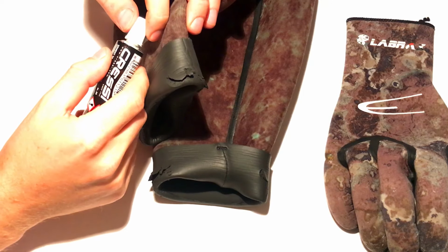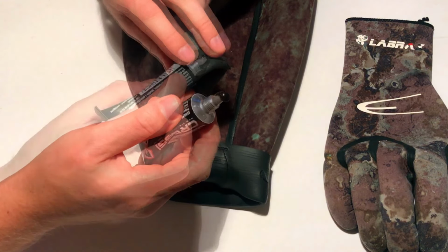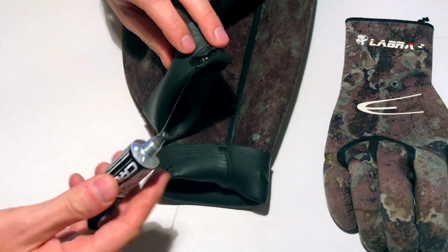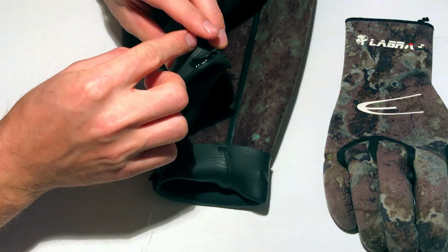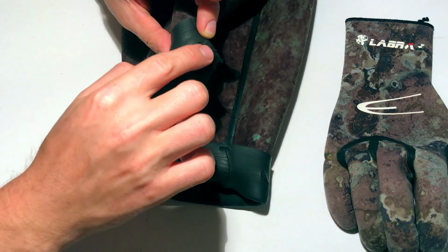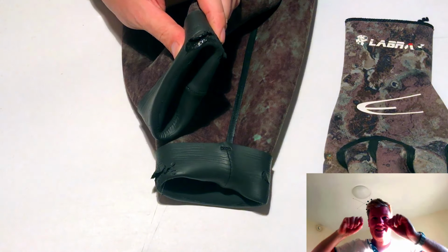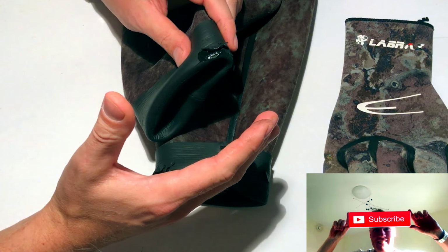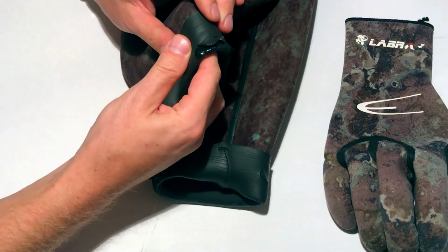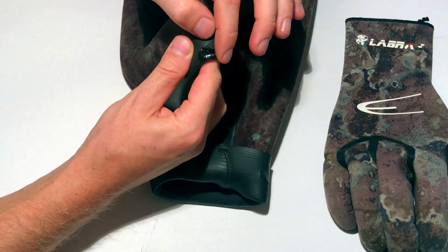Okay, in bad videos, they just tell you, yeah, you have to take the glue, put it there, and that's it. So this is wrong. You just need the neoprene. It doesn't even have to be completely dry, at least, let's say, hand dry, okay? So you put the glue on both sides of what you want to glue, okay? And then the most important part is that you wait until you press it together, because this glue works like when you repair the rubber of a bike. So it needs time to vulcanize, and afterwards just the pressure glues it together, not the time, okay?